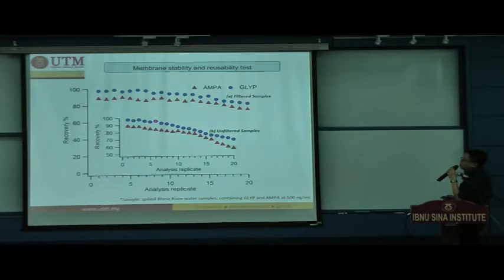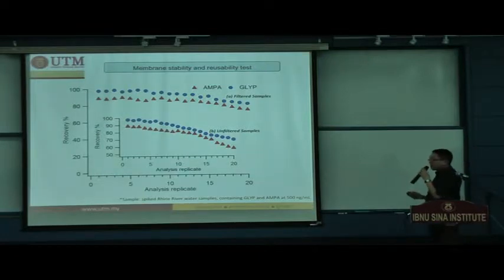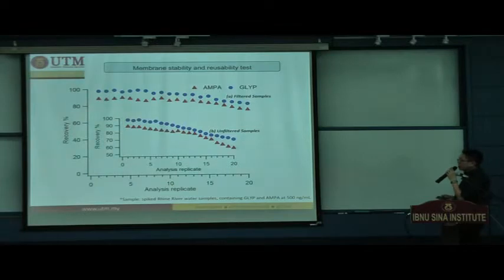And then the performance of the membrane starts to decrease continuously. This is due to the microparticles present in the river water. They started to accumulate on the surface of the membrane. And after 10 times of analysis, we can see that on the membrane surface, there are already some particles deposited on the surface, which reduce the active sites of the membrane that allow the ions to migrate. But this is very simple. We just put a membrane filter along the sample tubing during the sample flow-in. So it's not very tedious that you require a lot of manual work to filter the samples.